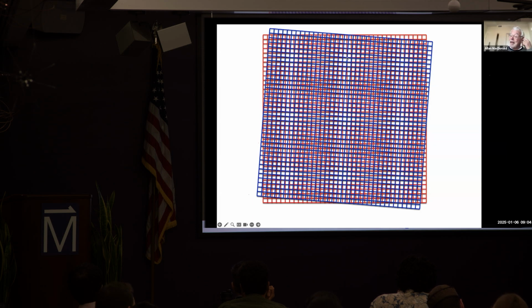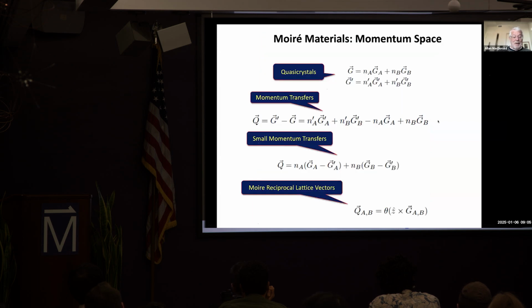What's going on at atomic length scale? One way of thinking about it physically is that if all of the electrons we're interested in are close together in momentum space, then they can't resolve structure in space on a length scale smaller than the range of momentum that is relevant. And by a Heisenberg uncertainty principle type argument, therefore they don't see what's going on at atomic scales. So the effective Hamiltonian depends only on the moiré pattern, and low energy states are described by a periodic Hamiltonian.